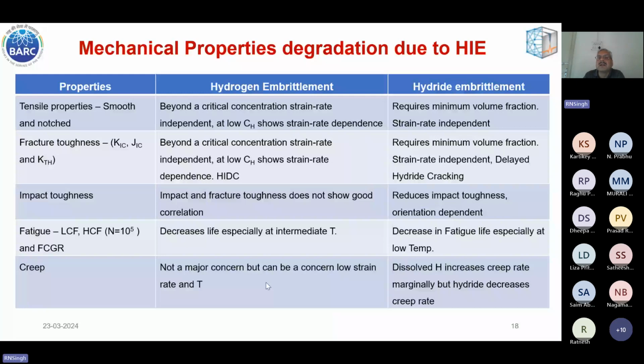On the other hand, hydride embrittlement requires a certain minimum volume fraction. Since hydride is what causes the embrittlement, it is strain rate independent. Fracture toughness also shows strain rate independent behavior. Delayed hydride cracking, as explained earlier, is caused by hydrogen migration near the crack tip under the hydrostatic stress gradient. Impact toughness is also reduced and is orientation dependent. I hope we'll have some illustration on this. Hydride is also known to decrease the fatigue life, especially at low temperature.